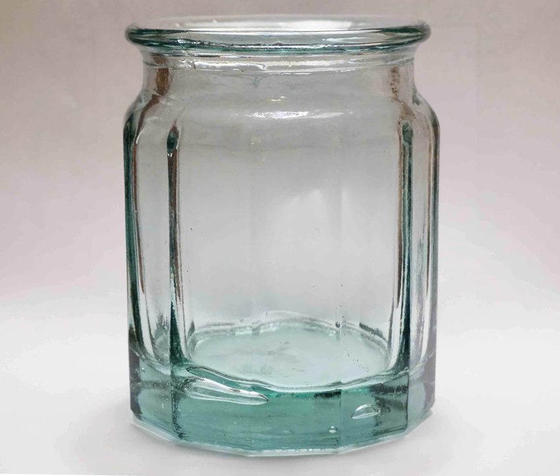The most common commercial glass types contain both alkali and alkaline earth ions, usually sodium and calcium, for easier processing and satisfying corrosion resistance. Corrosion resistance of glass can be increased by dealkalization, removal of the alkali ions from the glass surface by reaction with sulfur or fluorine compounds. Presence of alkaline metal ions has also a detrimental effect on the loss tangent of the glass, and on its electrical resistance. Glass manufactured for electronics, sealing, vacuum tubes, lamps, have to take this into account.